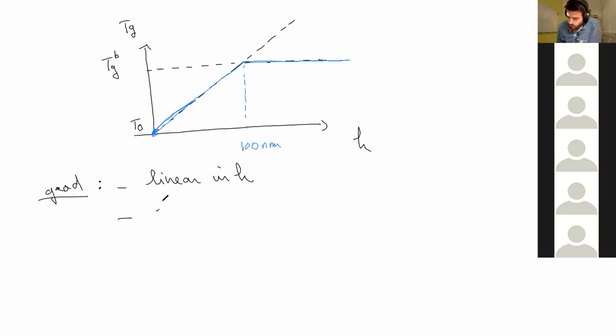We see H star, a typical value here, which is in the good order of magnitude. You see also that if H is bigger than this H star, then TG is always equal to TG bulk, no matter the size of the polymer chains and so on and so forth. So this is also a very robust experimental fact.